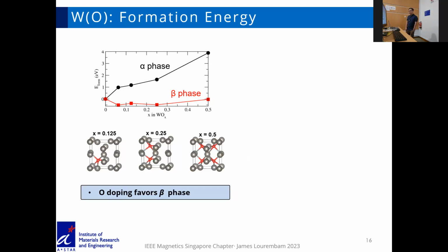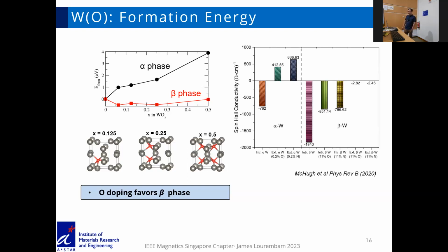So our collaborators at the IHPC looked into some DFT calculations and looked at the formation energy. What we found is that if we put in a little bit of oxygen, it helps. The black and the red plots are for alpha and beta phase. The lower the formation energy, the more stable it is. So if one puts in even a little bit of oxygen, it favors the formation of beta phase. However, previous work also showed from theoretical calculations that one wouldn't want to put too much oxygen in the system.